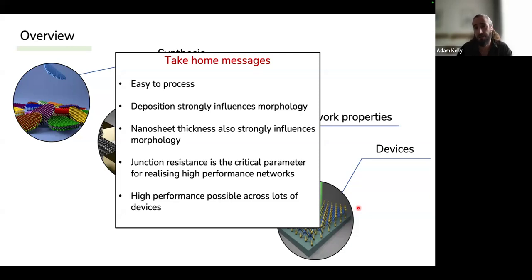If you have electrochemically exfoliated nanosheets, for example, and they're on a substrate, because they're quite large and thin, they adhere quite well, and you can usually just wash it then with IPA or something. So it's easy to remove these surfactants so you don't actually change the surface areas or surface energies of your materials.